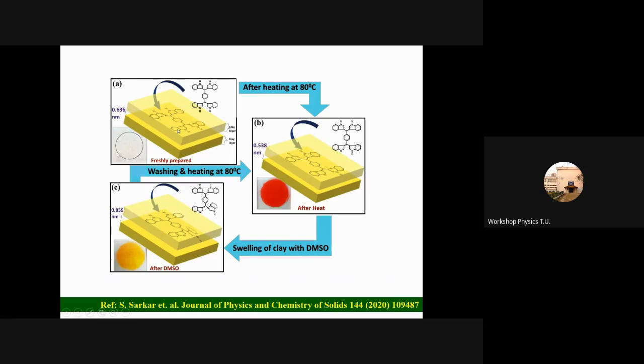And here in the schematic, we have shown the mechanism. Here you can see the molecule flat in the dried condition. This is the normally prepared condition. The layer height is 0.636 nanometer. This is again heated, and the gallery height decreases. That means maximum flattening occurred. A red color appeared. Here is swelling. Again, the gallery height increases, and this is done through XRD measurement, and twisting occurred.